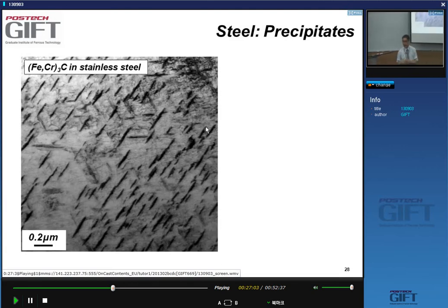And so you can see we have a complex situation, and part of the course will be devoted to trying to understand and determine and calculate how much loss of strength you get through precipitation of carbides, and how much increase of strength you get from the formation of these precipitates. It will turn out, just so you know in advance, that the solid solution strengthening by carbon in ferrite is very, very strong. So the result of this tempering treatment and the resulting carbide formation results in an overall reduction in strength, despite the formation of these carbides, okay?